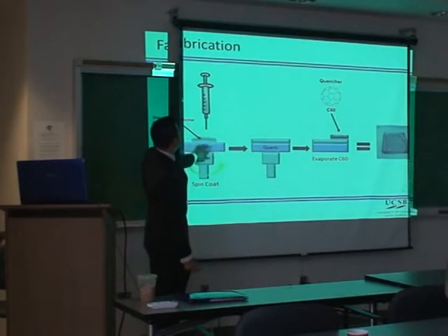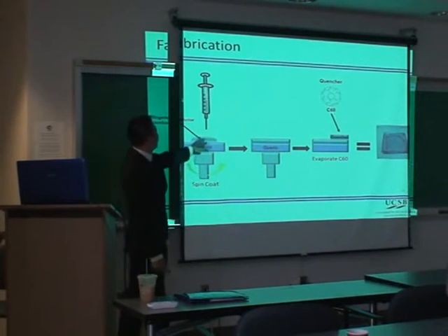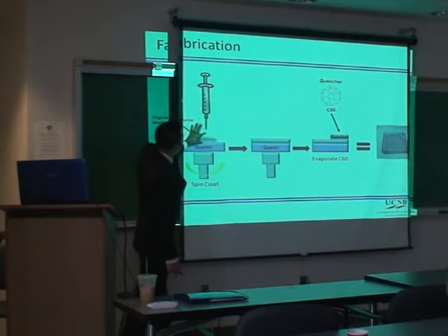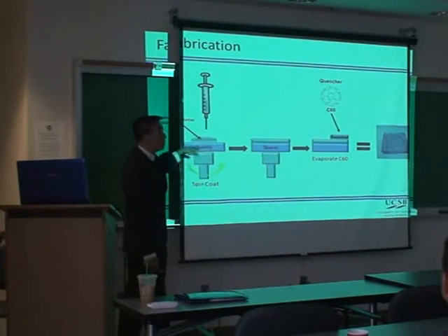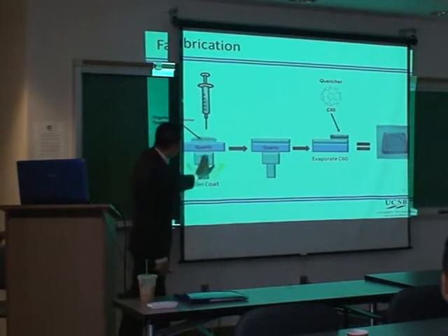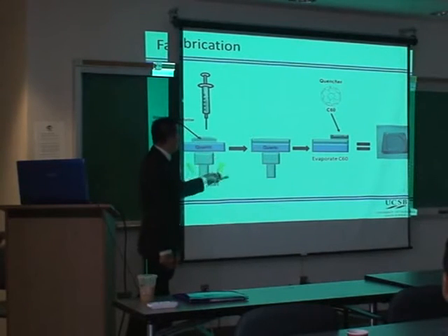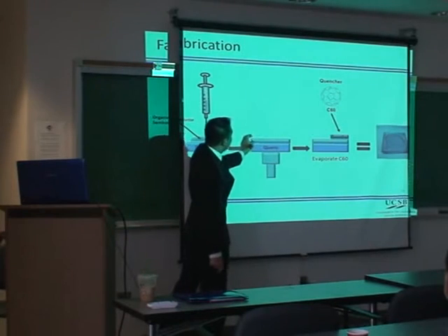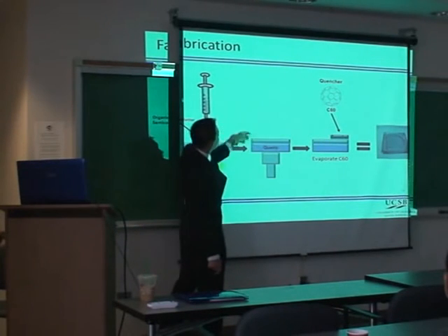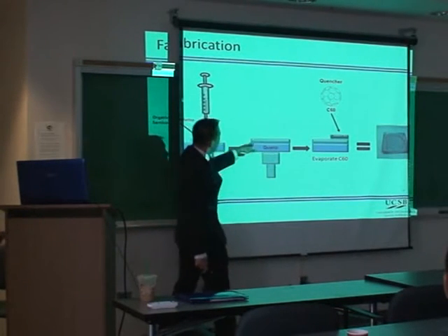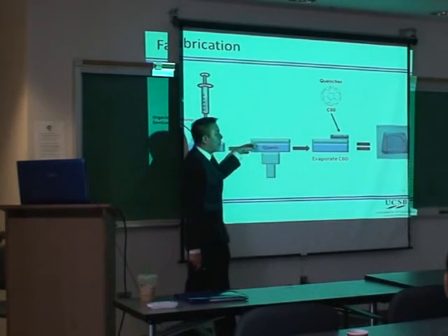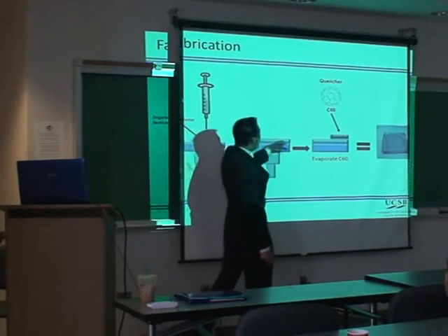Oh, geez, the colors are all messed up. Anyways, so what we first want to do is make a layer of our film. So we dissolve our organic material in an organic solvent, and we deposit it with a syringe on a substrate. We then put it on a motor that spins. This spins at a specific rate, and the rate that this spins will determine the thickness. In addition, this thickness is determined by the concentration of our solution that we start off with.